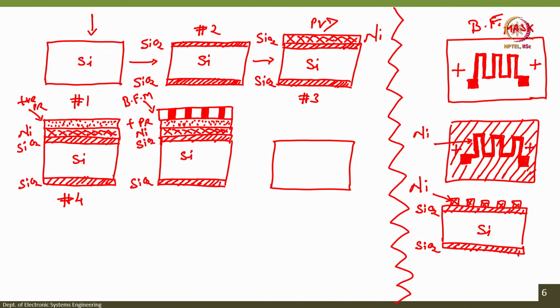then SiO2, correct. So, after pre-bake or soft bake at 95 degree centigrade for 1 minute on hot plate, we will align the mask, right, with respect to the wafer or wafer with respect to the mask, and then expose with UV light. This is UV light, right. After exposing with UV light, you have to unload the mask and develop the wafer, right. So, when you unload the mask and develop the wafer, what will you have?